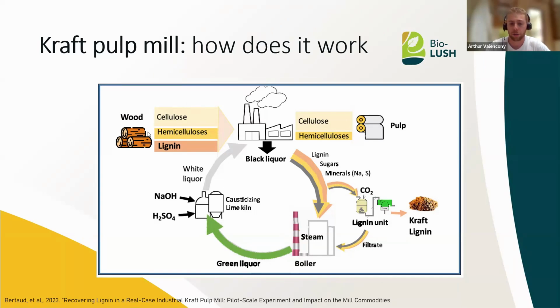Okay, so regarding the kraft pulp mill, we start from wood where we have separated the bark and the wood structure. In this wood, we have the three main components that go into the kraft pulp mill. On one side, the cellulose and hemicellulose pulp that can be converted into paper, for example, and on the other side, which is maybe the most complicated part of the kraft process, is the black liquor that is precipitated and evaporated to recover lignin, and also to recover the chemicals that we introduced before. These chemicals are recovered into the green liquor, which is improved to obtain white liquor again, that is introduced again in the kraft cooking.